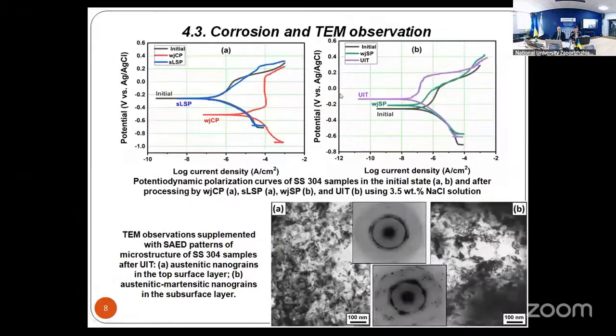The significant improvement in corrosion resistance and impact treatment induced oxidation of metal components was obtained by the ultrasonic impact treatment methods, and it's in good agreement with previous works. The severe plastic deformation of the near surface layers by the multi-pin ultrasonic process resulted in more strain-induced martensite and flatter surface texture with low roughness than the cavitation, laser, and wet shot deformed samples. Also, all the studied samples are characterized by some passivation region.